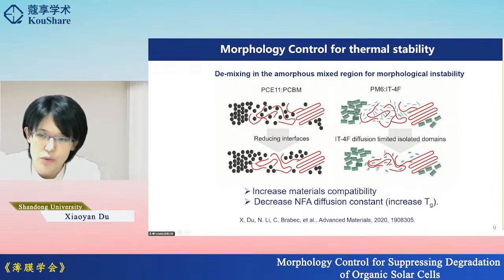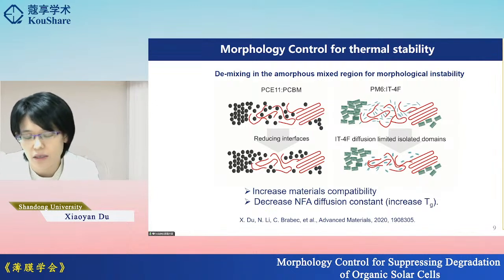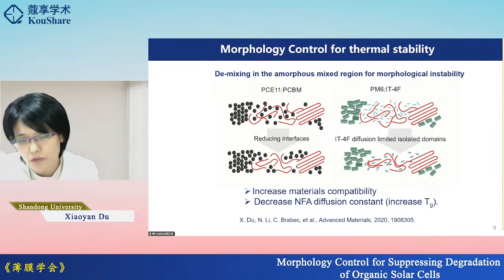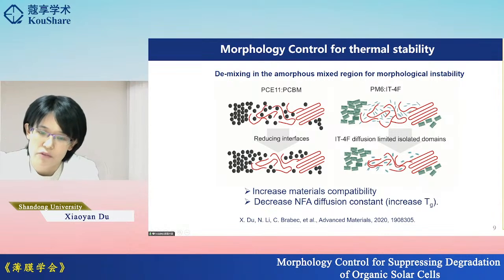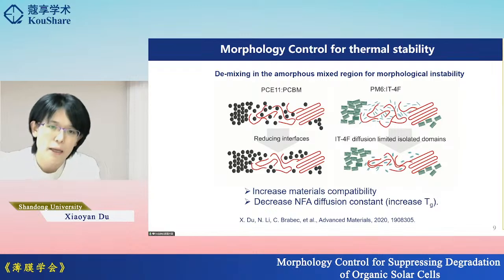And the way to overcome this, or to suppress this degradation, is to increase the miscibility or compatibility of the donor and acceptor materials, and also to suppress or decrease the diffusion of these non-fullerene acceptors by increasing the Tg for these materials. And for the